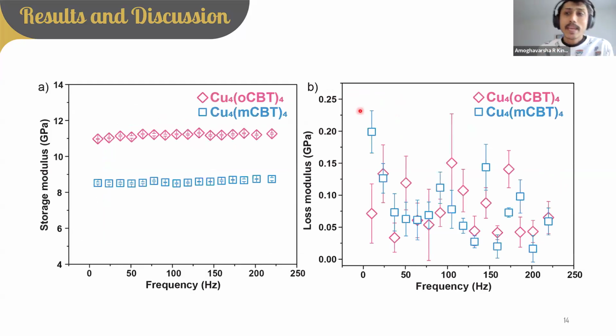Then coming to dynamic mechanical analysis. The measurements which we have done until now is just indenting the sample and then taking out the tip without any vibrations given to the tip. So this is called a quasi-static measurement. But in this one, we are doing dynamic mechanical analysis, where we provide a certain frequency to the tip, and we measured from 10 hertz up to 220 hertz. And we get the storage modulus and loss modulus values.